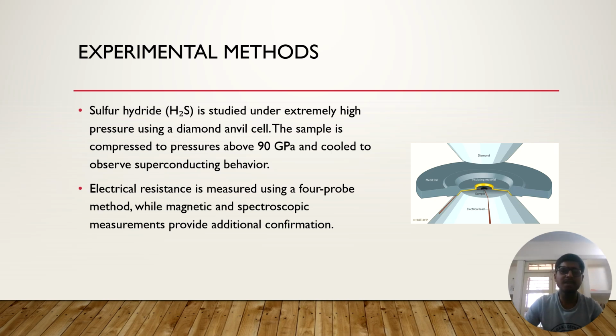The sample is typically loaded along with a pressure transmitting medium to ensure uniform compression. Pressure calibration is often carried out using standard techniques such as ruby fluorescence. Once the desired pressure is achieved, the sample is gradually cooled to observe the superconducting transition. The primary measurement used is the four-probe resistance method. In this technique, four electrical contacts are attached to the sample, two for passing current and two for measuring voltage. This configuration eliminates contact resistance and allows precise measurement of intrinsic electrical resistance.